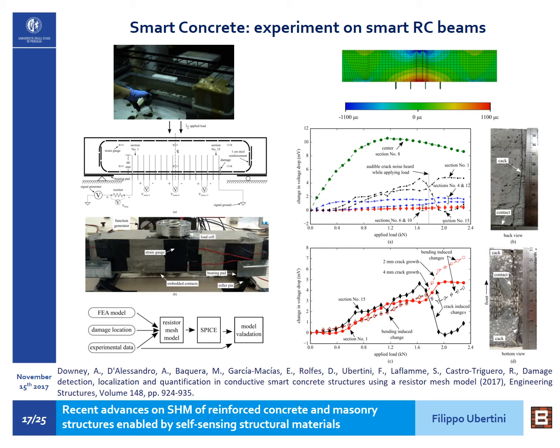To demonstrate this in more detail, here is another experiment referring to a small beam made of cement paste with carbon nanotubes, reinforced only with longitudinal reinforcement to anticipate a cracking in shear, and subject to a 4-point bending loading condition. On the diagrams on the right, you see the change in voltage drop as a function of the applied load for different sections, for different pairs of electrodes along the beam. What we see in these results is that